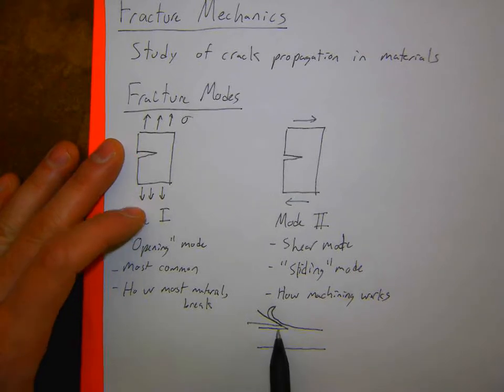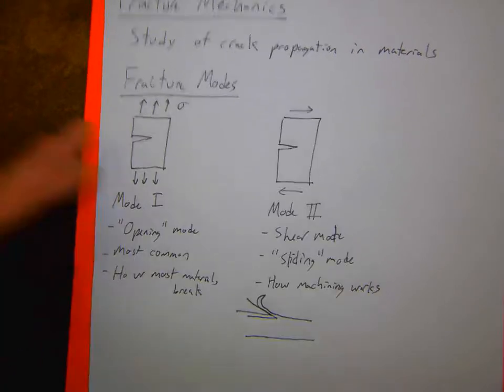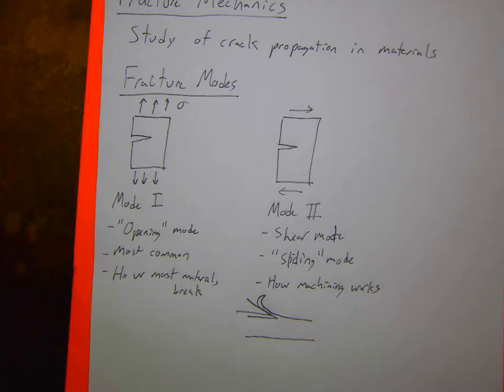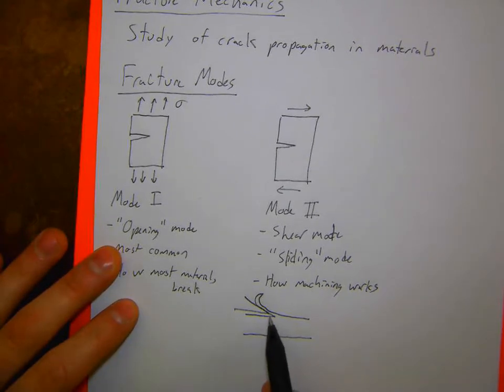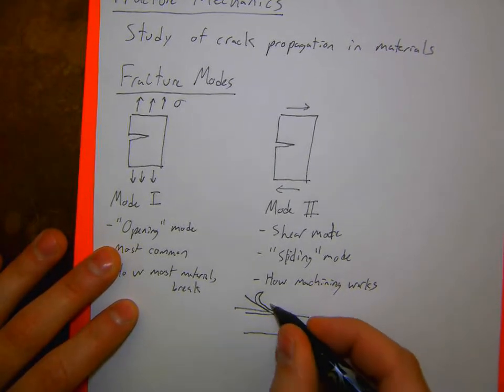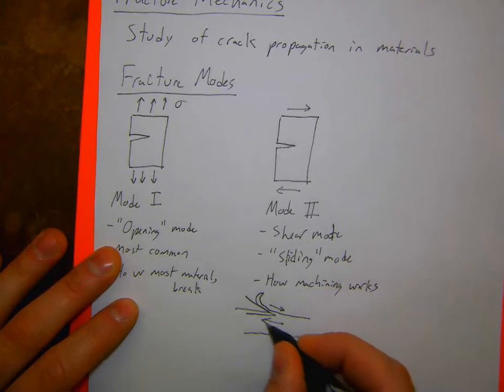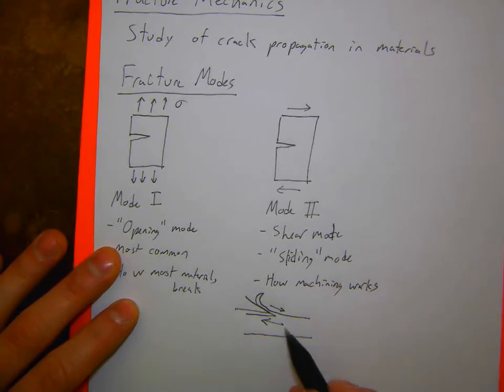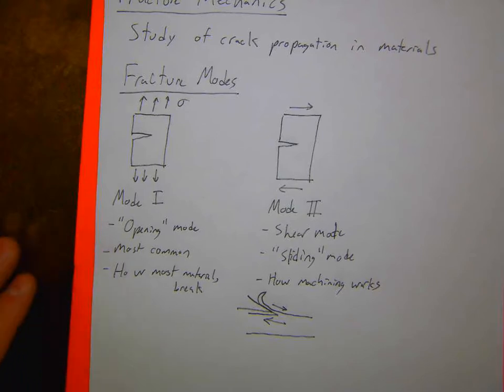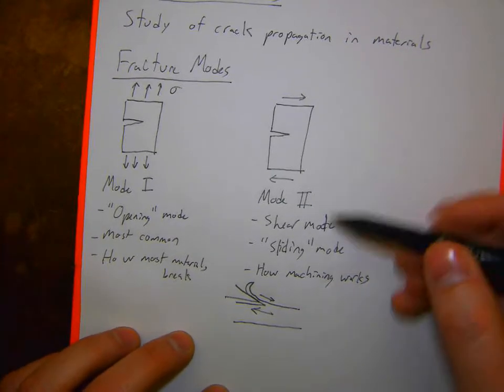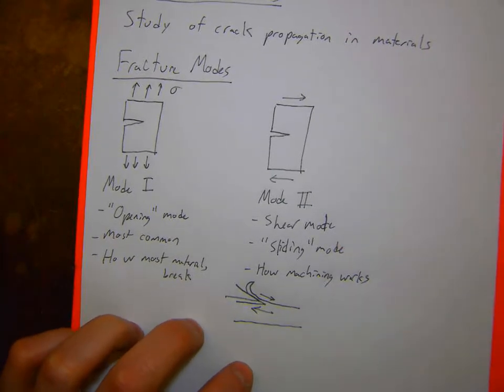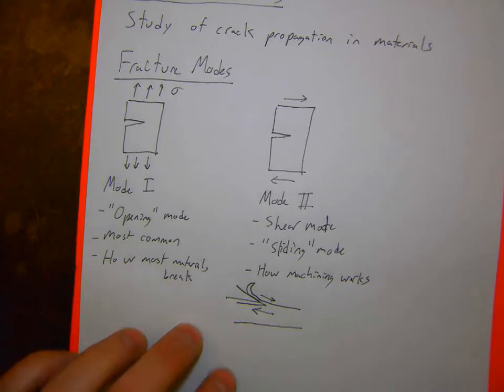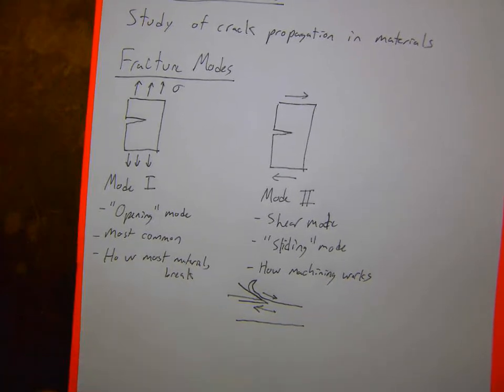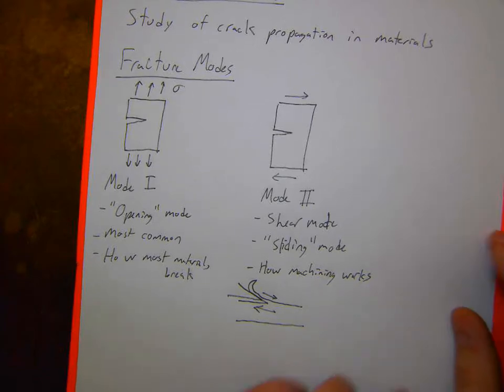This is actually a mode 2 fracture. So it's causing a shear on the surface that's then causing fracture to happen. So you can imagine now there's kind of a shear stress here that's forcing this material to fracture. And so depending on the shear, or the mode 2 shear fracture resistance of the material, it's easier or more difficult to machine. You actually want something that's sort of ductile so it doesn't just shatter, but not too tough that it is impossible to break.